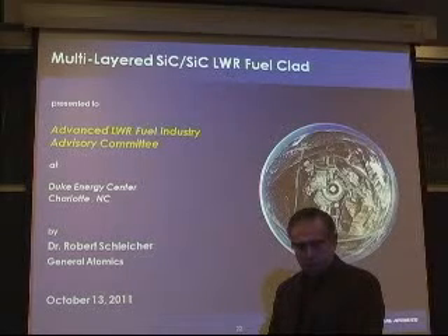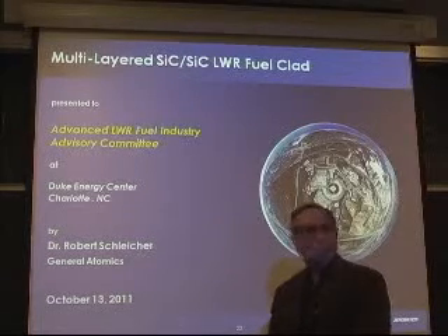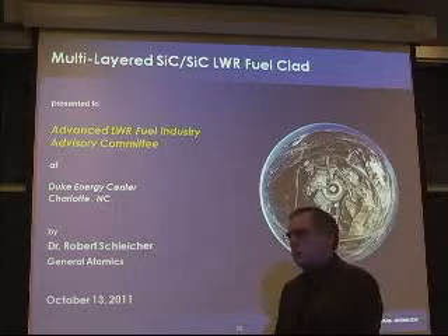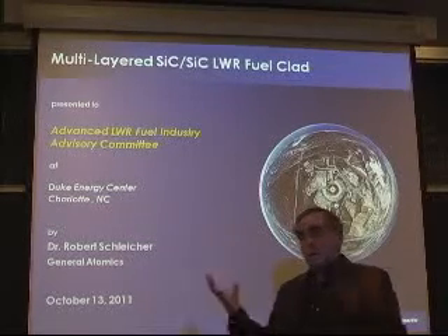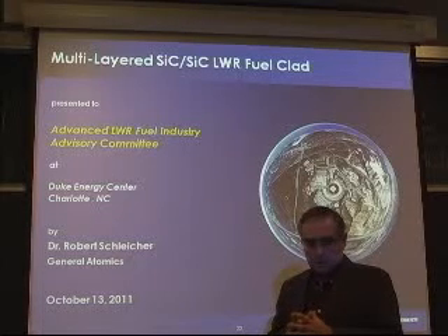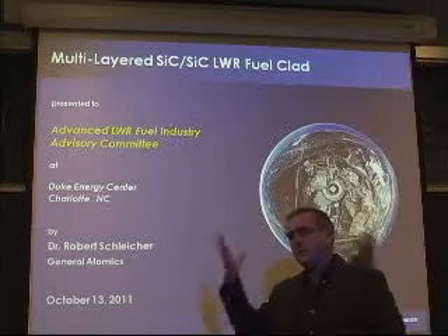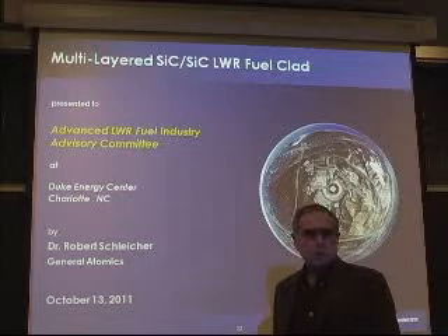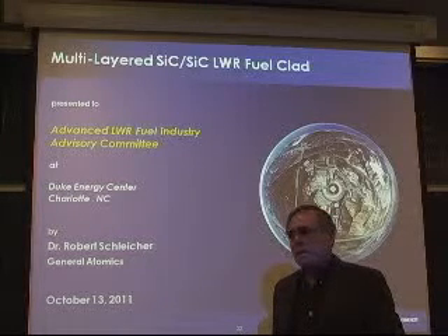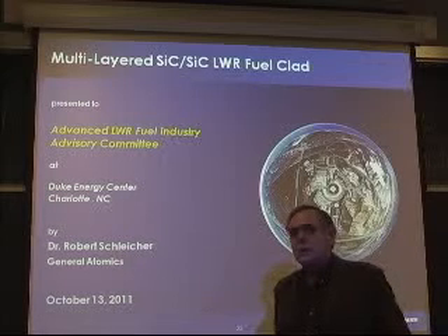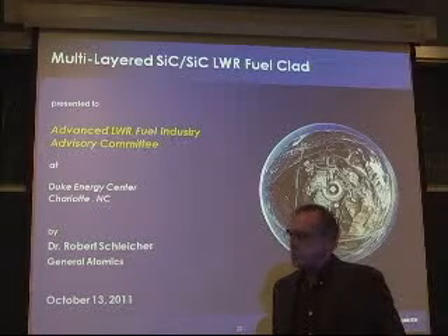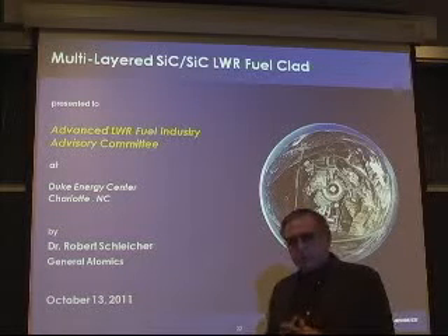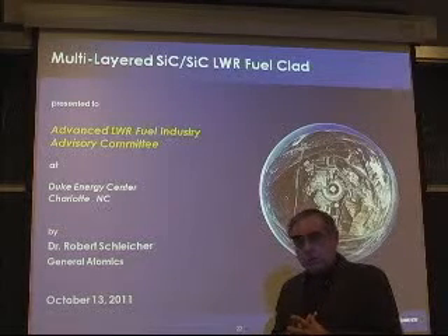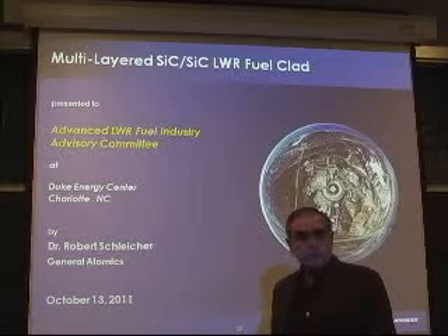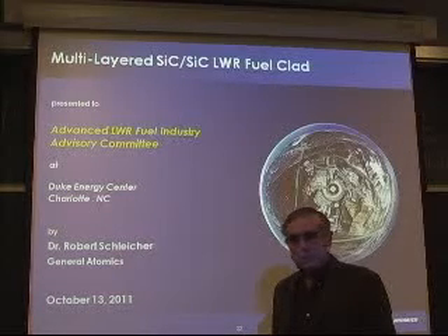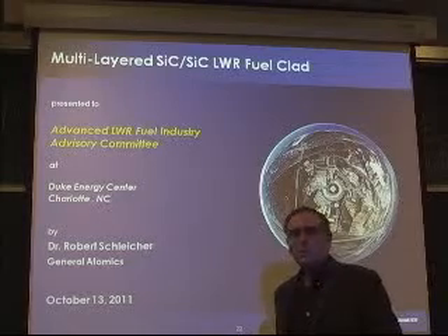And because of Fukushima, there's a lot of focus on silicon carbide for cladding for light water reactors, because it turns out that silicon carbide reactions with water are several orders of magnitude slower than zircaloy. So you can effectively say that generation of hydrogen in an accident condition will not occur. Now, that could be a game-changing idea if we could make cladding cheap enough. And that's something we're really geared to do right now. We've committed, and we're trying to do this.